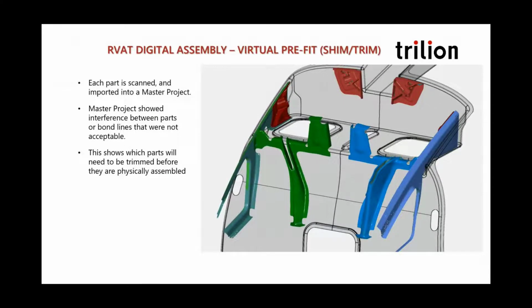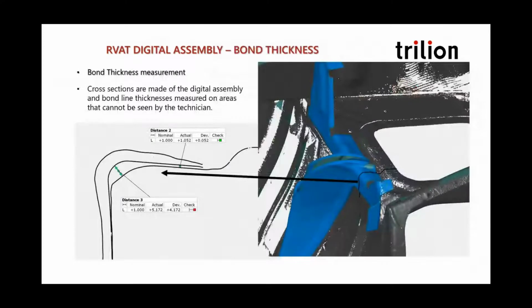So in digital fabrication, we're doing a lot of work with pre-fit shim and trim calculations. We can scan each part, put them together, and make sure whether a shim or a trim is required. Then during manufacturing, we can measure the bond line thickness. This is done on every structure at General Atomics, where they validate that the part is meeting the requirements. A too thin bond will not hold, a too thick bond will not hold. So making sure your bond is correct.